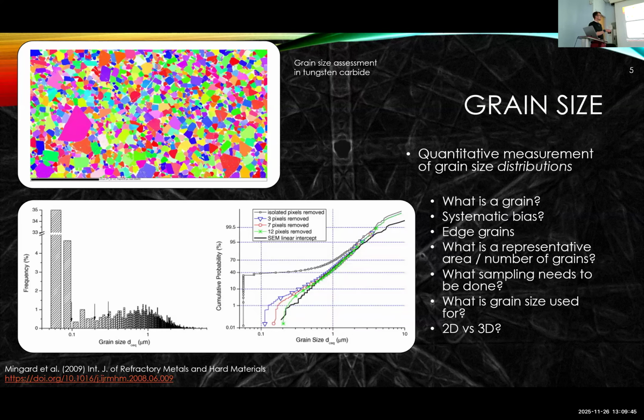So they've been working over many years to develop standards to understand the population of grains in that material, how you sift and mix those different raw precursors, how you then put things like cobalt and chromium binders into the system to create a material that is both strong and tough, despite it being made of a cemented carbide. And so we can now get a huge number of grains that are mapped that enable us to access really great contrast. We can segment each individual grain, count the size and shape of that individual ensemble, and apply statistical analysis. These are the cumulative distribution functions to ask, what does the distribution look like? It's not a single number. It's described by some population where we have something like a skew distribution for that particular population of grain sizes in this two-dimensional section of the material.